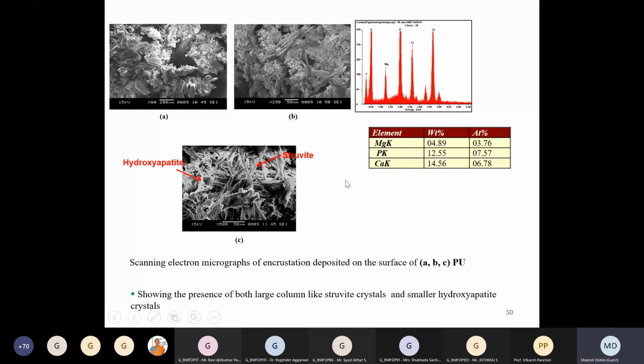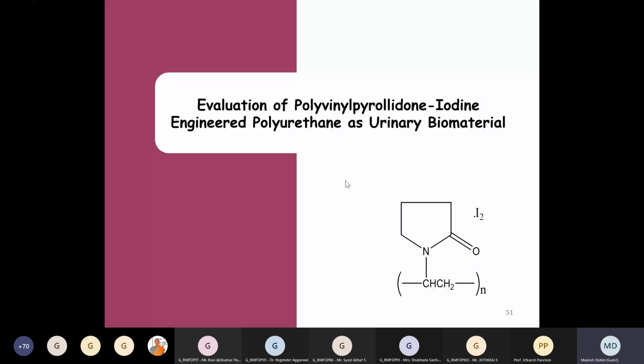Okay, so what we started doing is we thought of a polymer called polyvinyl pyrrolidone iodine. This is a polymer that contains iodine and slowly releases iodine over a period of time. And as you know, iodine can be antibacterial. So when we coat the polyurethane with this particular polymer, as the iodine slowly gets released over time, you have an antibacterial surface. The main advantage is we can prevent bacteria from getting attached. So we modified the surface with this polymer. This is called surface modification.